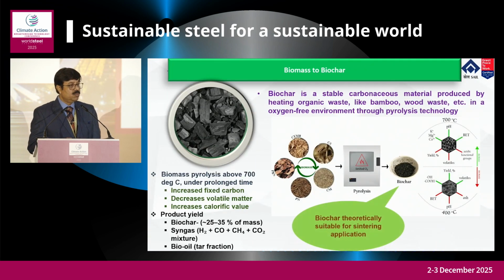Now, this is the biomass to biochar. Basically, biochar is a stable carbonaceous material produced by heating organic waste like bamboo and wood waste in an oxygen-free environment through pyrolysis technology. Now, biochar is theoretically suitable for sintering application. Now, what is biochar? Biochar is the product of burning of bamboo in a low or absolutely oxygen-free environment.